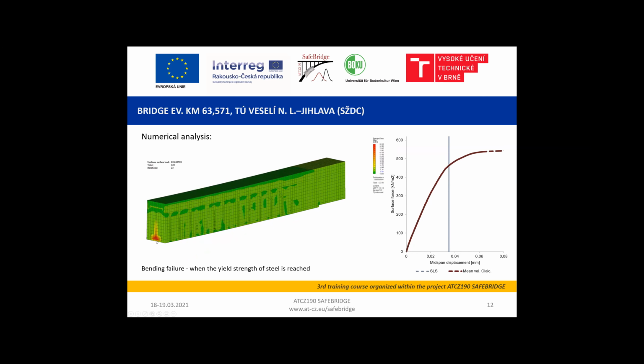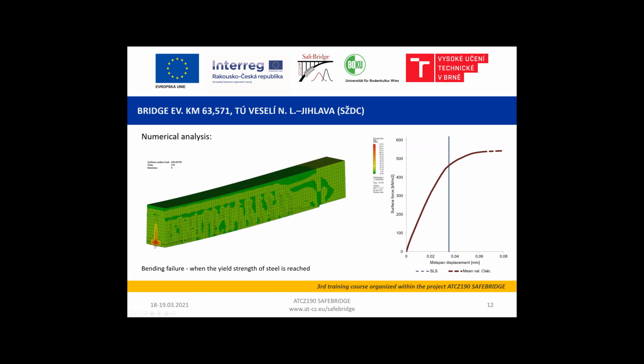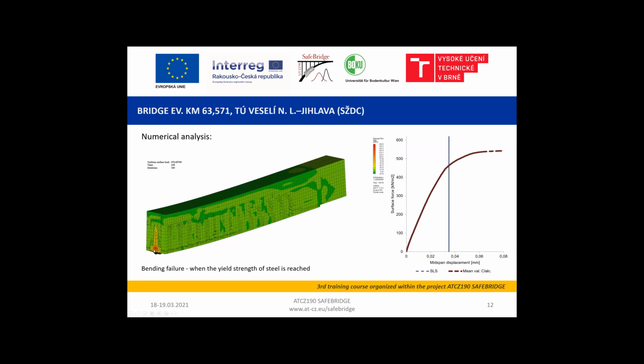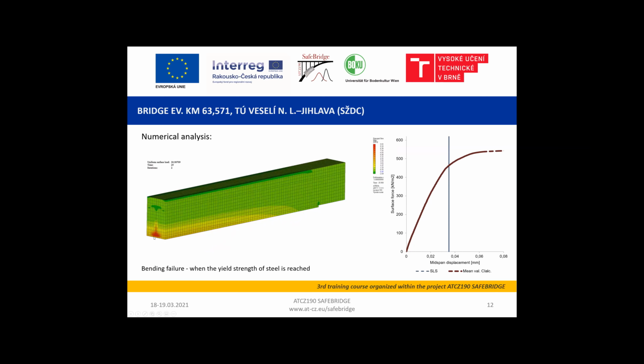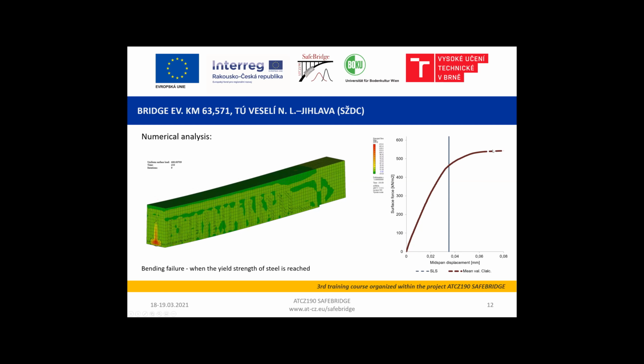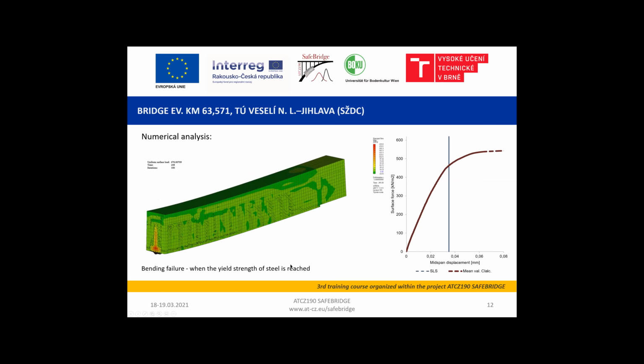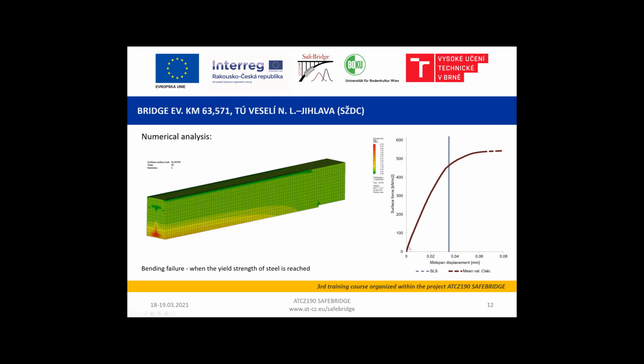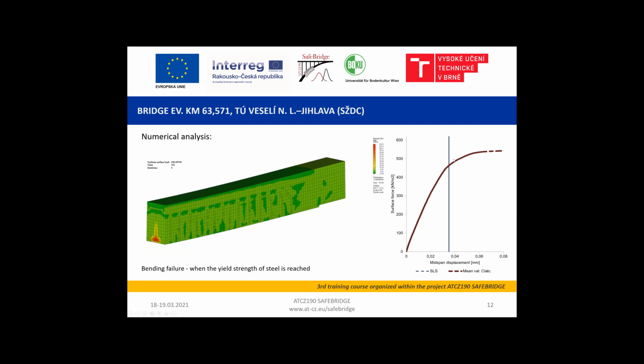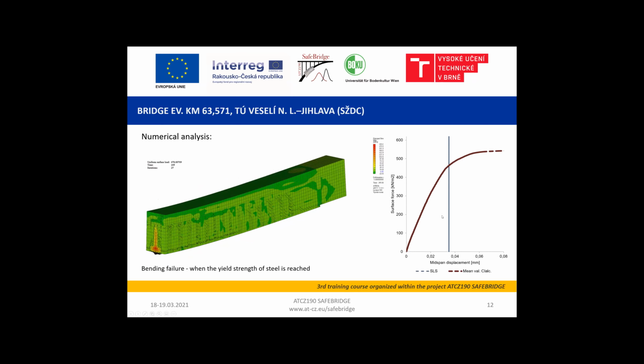As expected, the most decisive parameter of analysis is, of course, the yield strength of the steel. The concrete itself helps just to distribute the loads, but for this type of construction the steel is the most crucial factor. Here you can see load deflection curve, which represents this situation, and it's calculated for a numerical model with mean values of material parameters assumed. Also here the serviceability limit state is marked, which corresponds to 35 millimeters according to Eurocode 2.